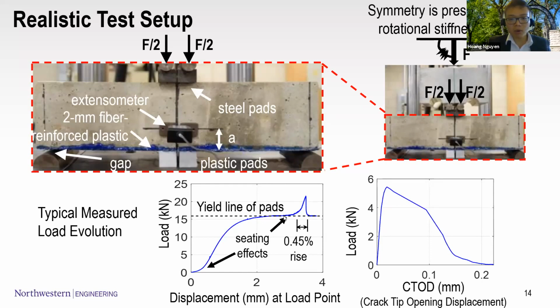And then after a while, it touched the support, the side support, and the moment to trigger the opening mode of fracture will cause another rise. So the requirement here is that you have to leave the gap so that the fully plastic strain is developed within the pad. And you can confirm that after the specimen broke up, you see the drop back to the plateau.